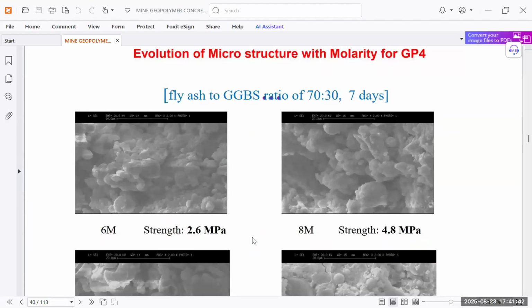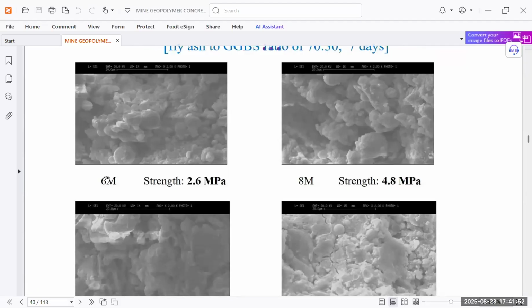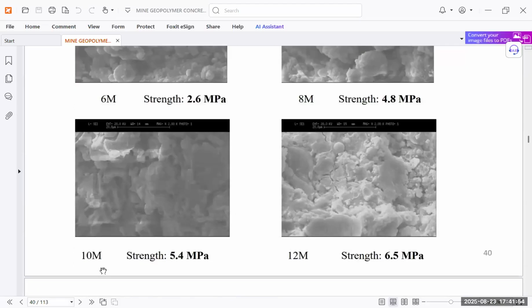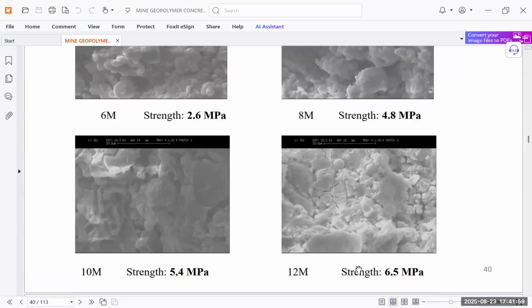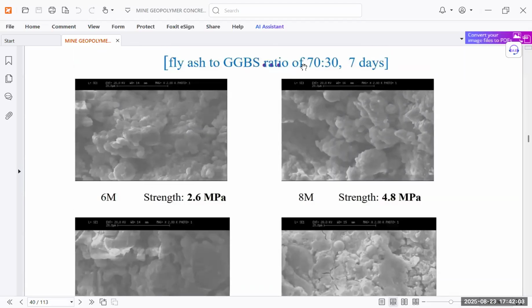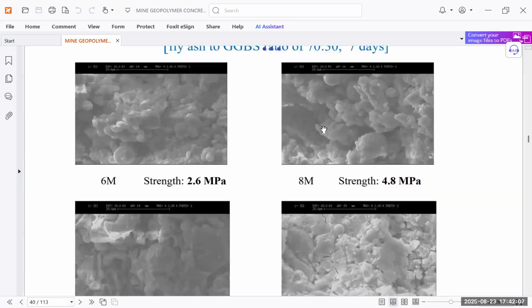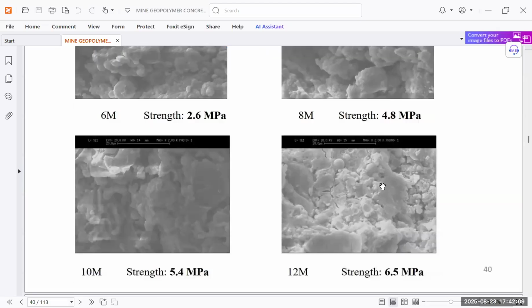So by controlling the molarity also, we can get different strength for the same number of days. That is also one part. As per the requirement, we can mold the different molarities. Whatever strength we want to achieve in 7 days, we can accordingly make the molarity 6, 8, or 10 or 12, as we have tried here. You can see 7 days strength is 6.5 megapascal for the same fly ash to GGBS ratio, 70 to 30. That is the reason why it is also moldable.